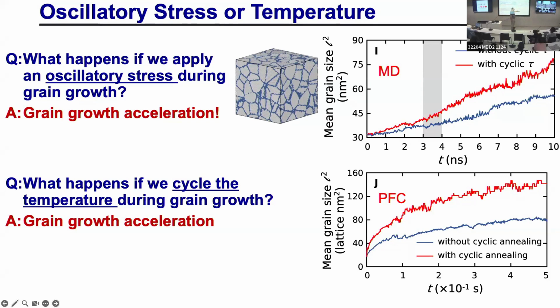So if I held it at, say, 500 for 10 minutes, and then I held it at 400 for 10 minutes, you get a curve like that. But when you oscillate it, it's like that. Now, a couple questions. What frequency do I have to oscillate the temperature or the stress? Well, if I do it at zero frequency, there's no effect. If I do it at infinite frequency, there's also no effect. So there's a maximum somewhere in between. And unfortunately, as of right now, I don't know where that maximum is.